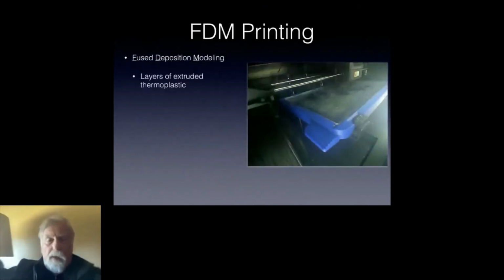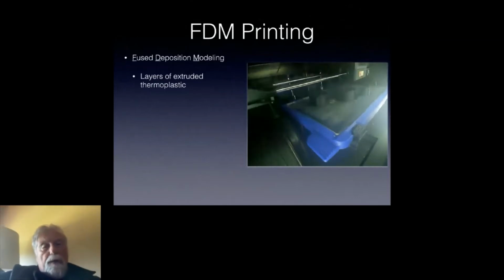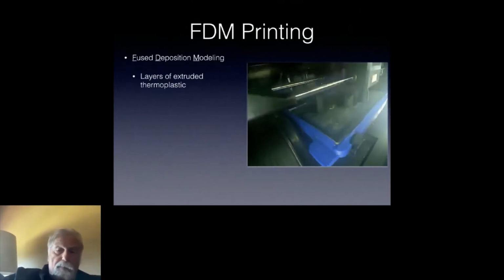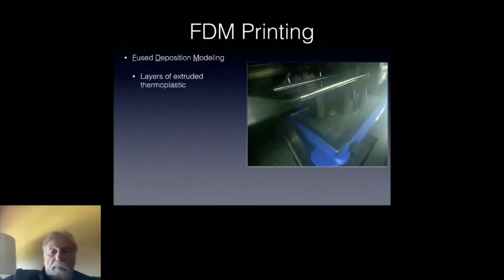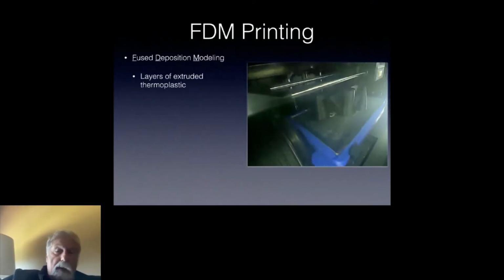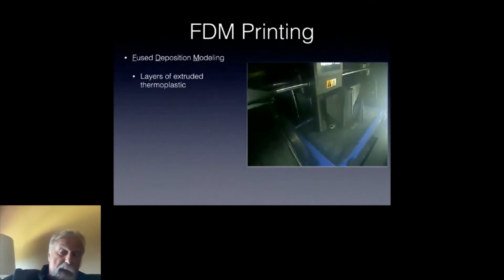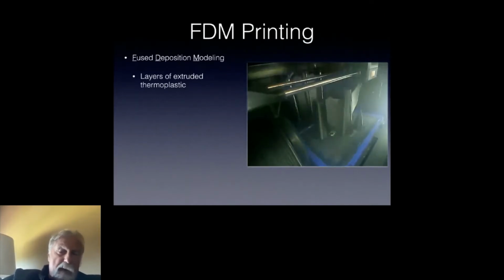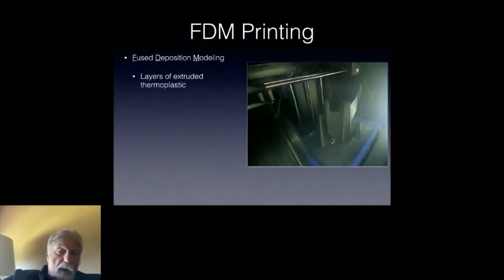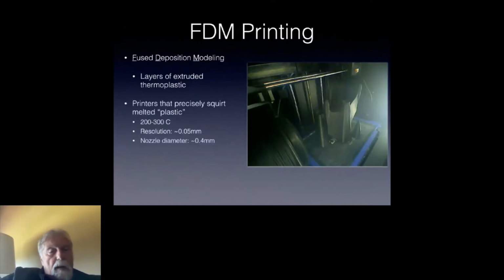So the core technology accessible to amateurs is called fused deposition modeling. And you can see hopefully a video on the side of my printer physically printing out a complete airframe. It does it by layers of extruded plastic. You can see the print platform moves in the Z direction, and the print head moves in the XY direction to essentially print extruded thermoplastic. The plastic, of varying materials, is generally between 200 and 300 degrees C at the print head, with a resolution on the order of 0.05 millimeters, with a nozzle diameter, so a feature size, of about 0.4 millimeters.